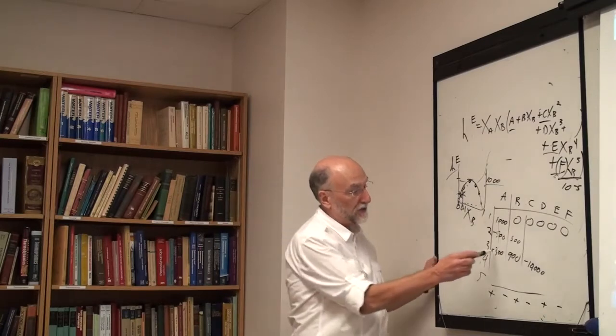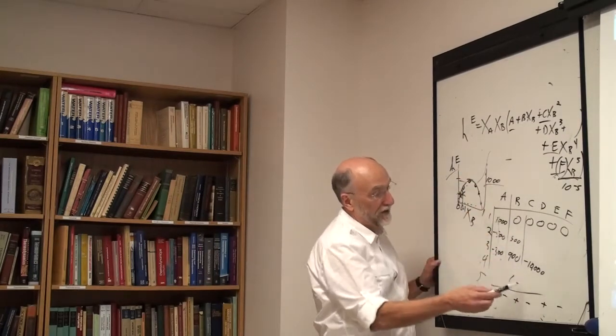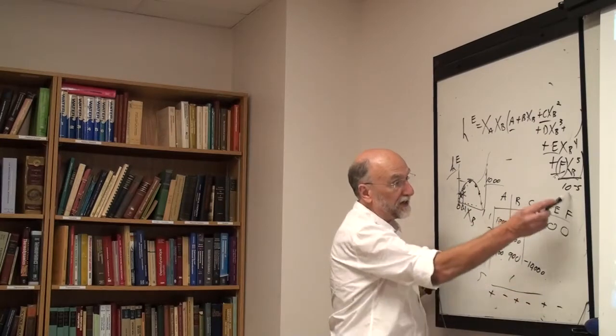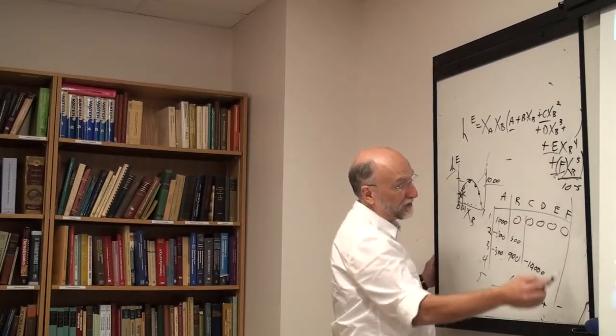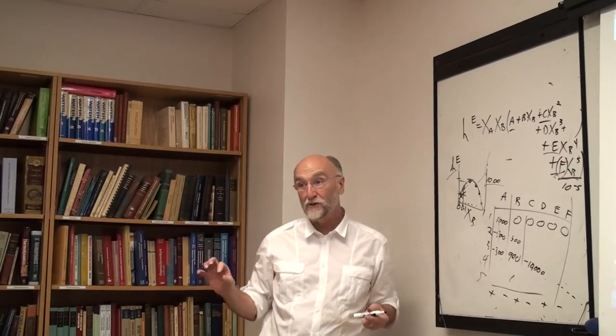So what you find is the terms have no significance. Each individual term has no significance. The terms get larger and larger and larger. You get out to something like the 7th term, and you've got something like 12 or 13 significant figures, all of which must be stored in your data file.